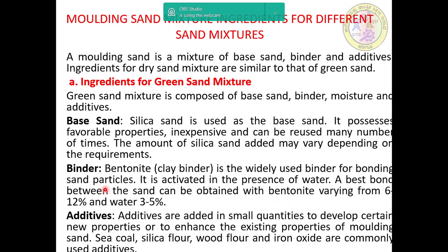And then binder, which is nothing but clay. Usually a clay, that is bentonite, is the widely used binder for bonding the sand particles. It is activated in the presence of water. The best bond between the sand can be achieved with bentonite varying from 6 to 12%, and then water is around 3 to 5%.